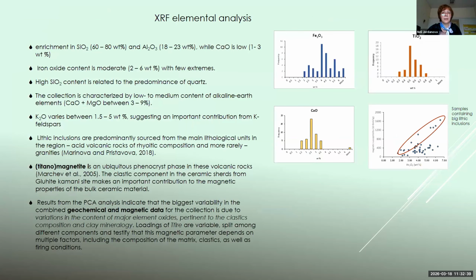We also carried out elemental analysis, which proved that the major element content is governed by the composition of the lithic inclusions in the ceramics, which come from the acid volcanic rocks in the near environment of the site, which was in agreement with different other analyses from the geochemistry.